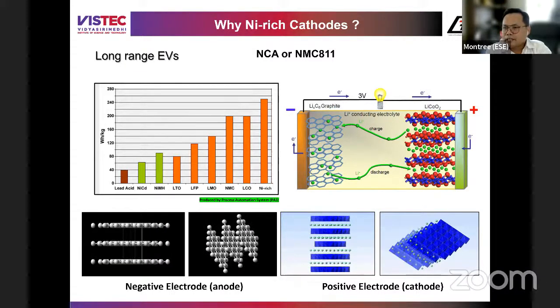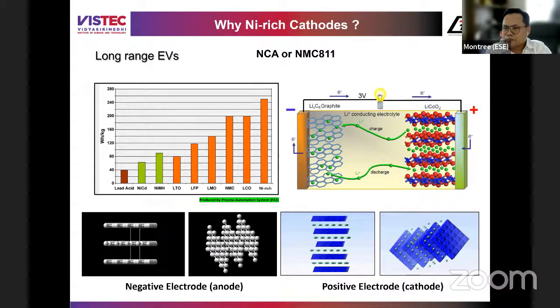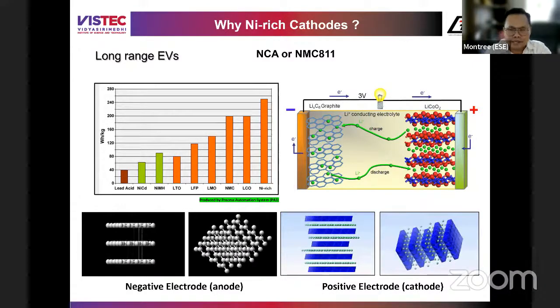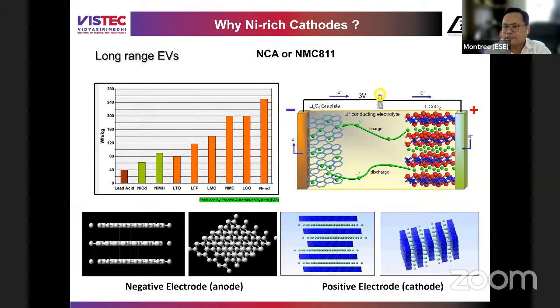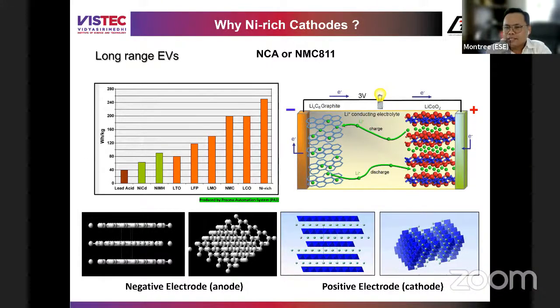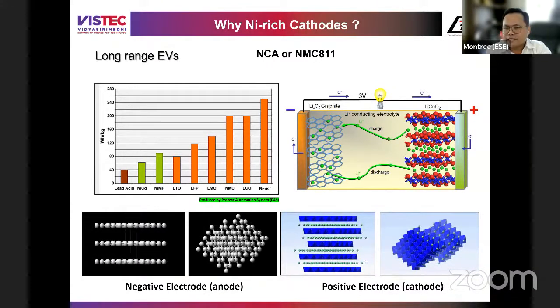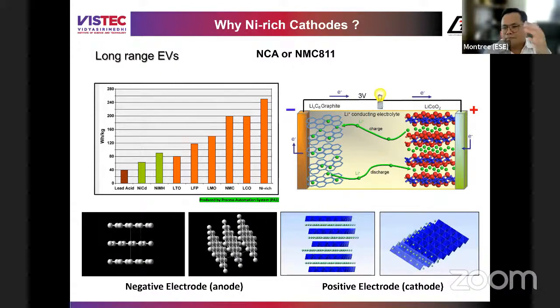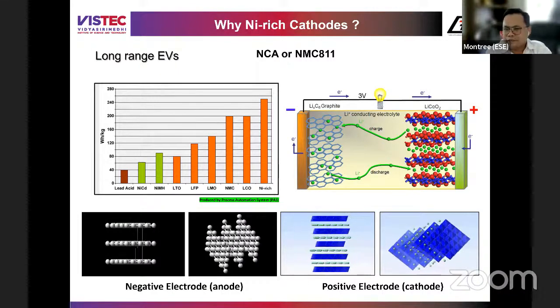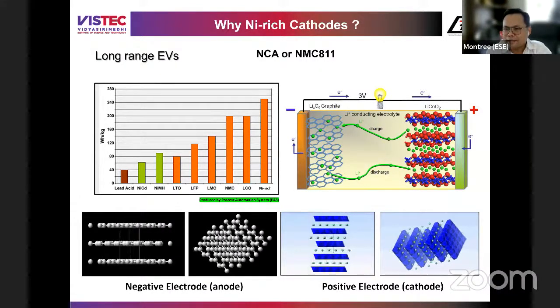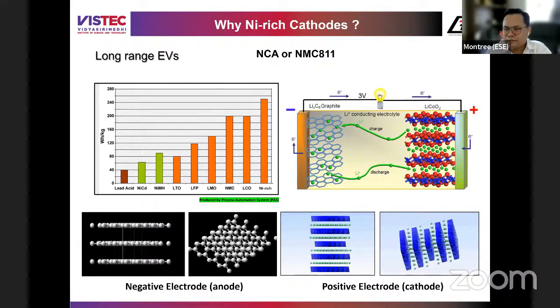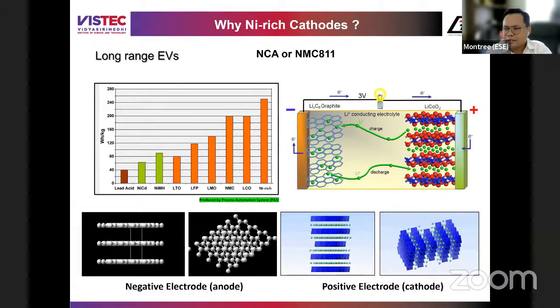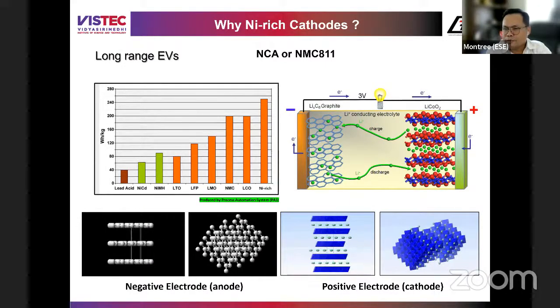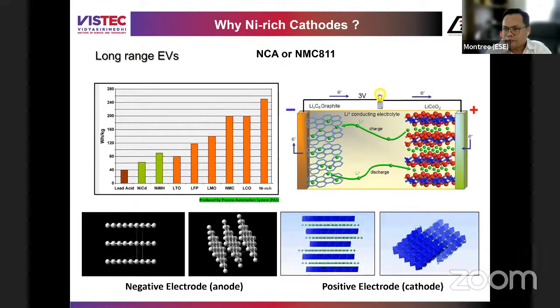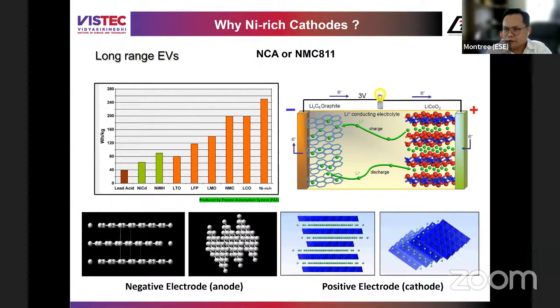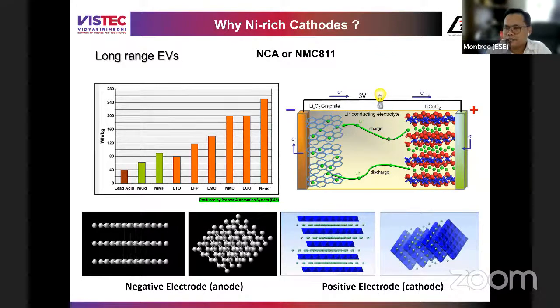And here, lithium forms lithium cobalt oxide, which got John B. Goodenough recognized as the father of the lithium-ion battery. Here you can see the animation. When I say graphite, we have millions of sheets of graphene, and we have space there to hold the lithium when we do charging. On the other hand, at the positive electrode, we have layered materials like LCO, NMC, NCA,